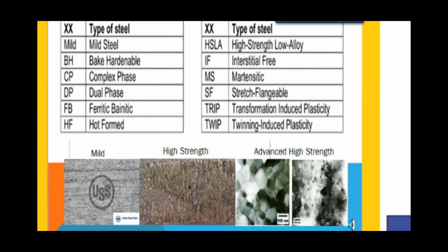And in the 70s, when the corporate average fuel economy was first made by the government to increase vehicle mileage, the manufacturer had to rethink about steel. That's when the HSLA steel started coming out. And what you see with that is a much tighter grain structure. The tighter the grain structure, the stronger that steel will be. In this case, with a yield strength of approximately 70,000 pounds per square inch of pressure to pull high-strength steel apart.